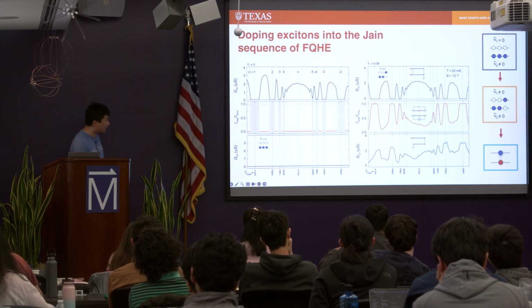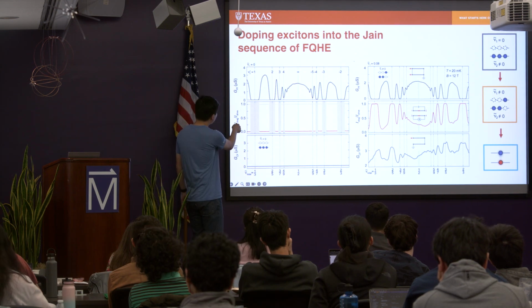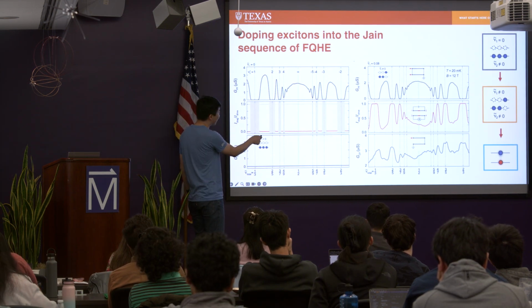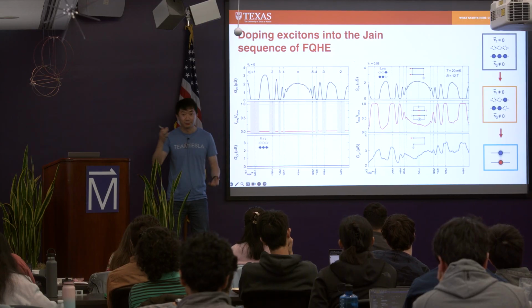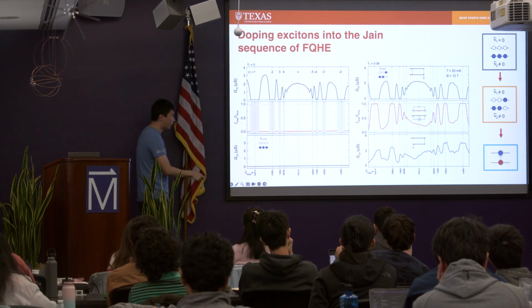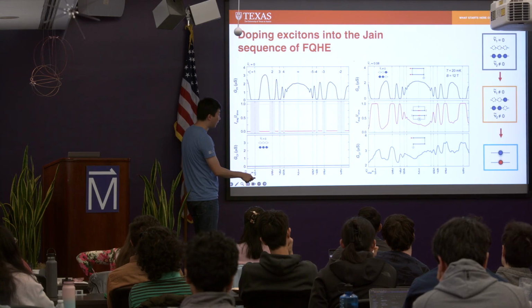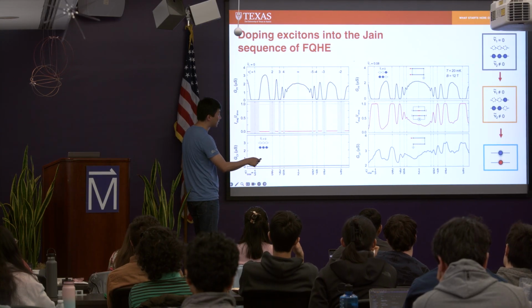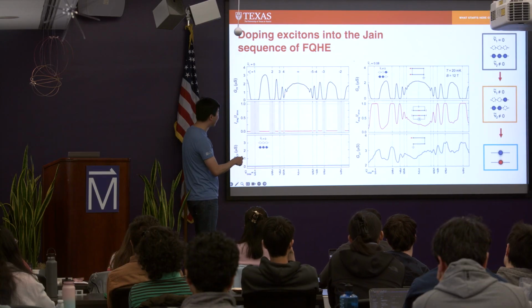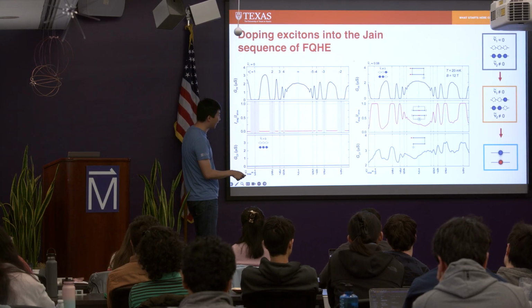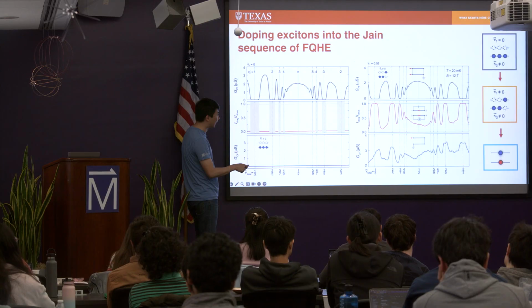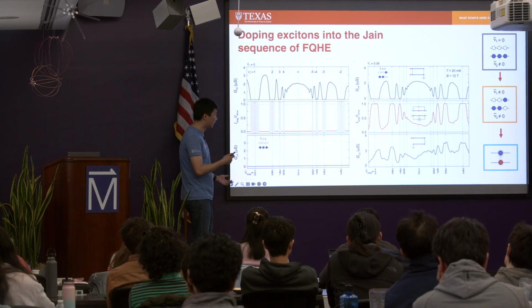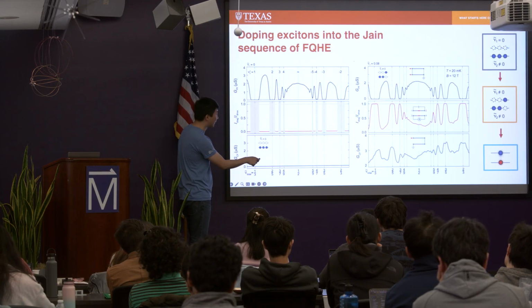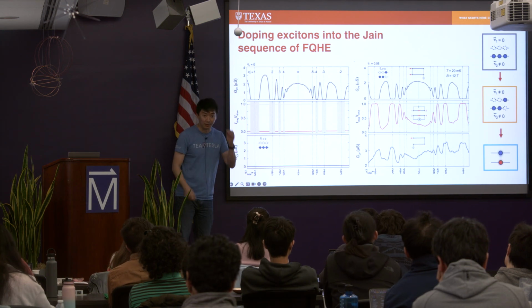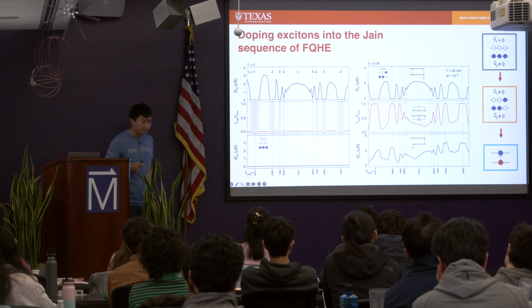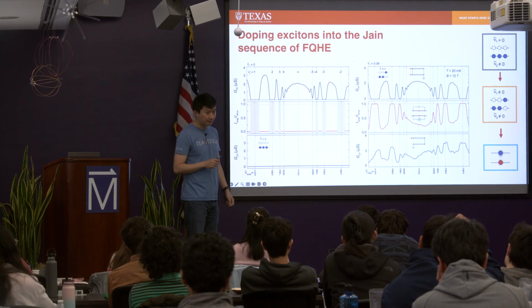And this is the data. In this case, nu 1 is 0, and here we increase nu 1 just a little bit, 0.08, to fill about 10% of the Landau level. And we're sweeping total filling across the two layers. And in the parallel flow channel, you see all these same states forming. That looks identical to this. But now you start to see counterflow starting to form peaks when parallel flow is 0. If you plot the drag measurement at each of these fractional quantum Hall effects, you start to see perfect drag response. Yeah. So the excitons here, they're not condensed?